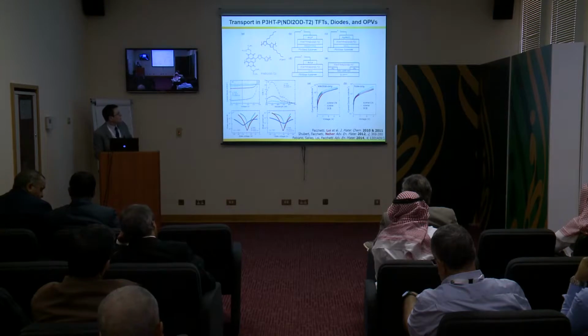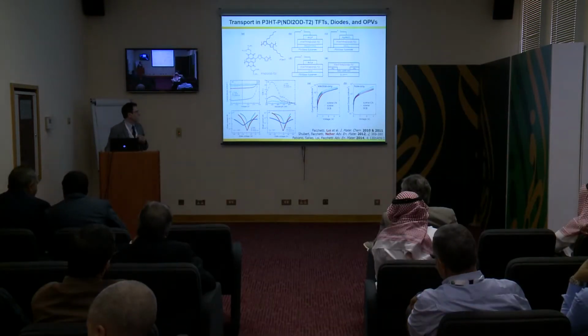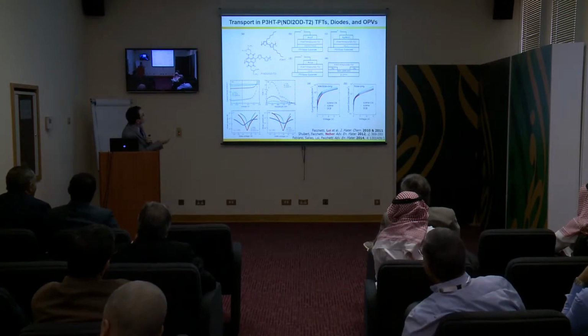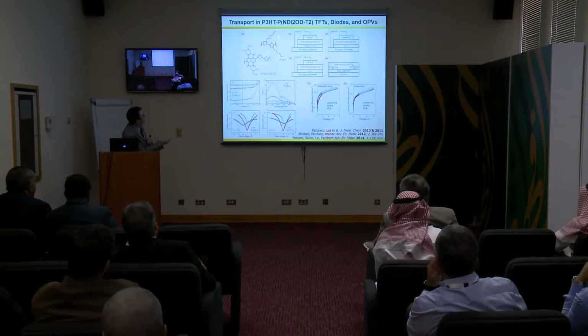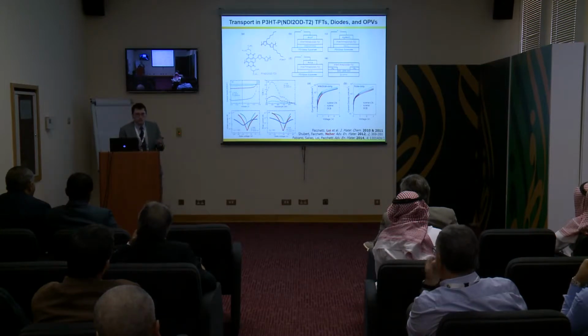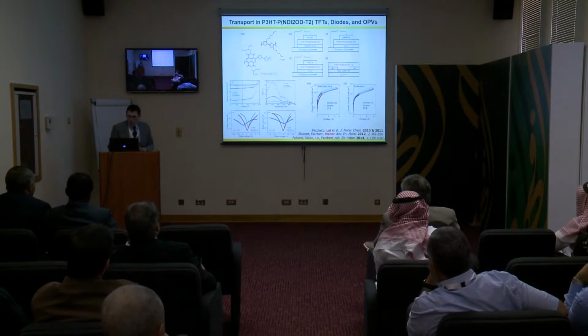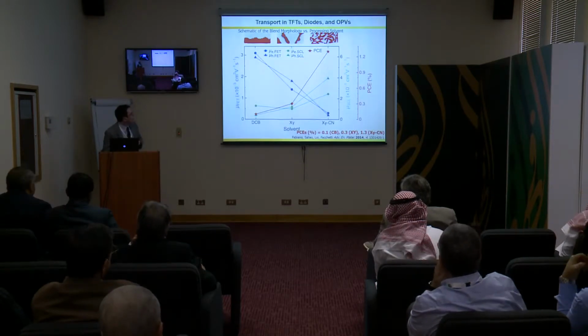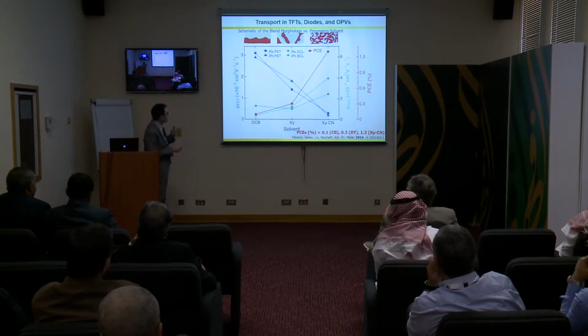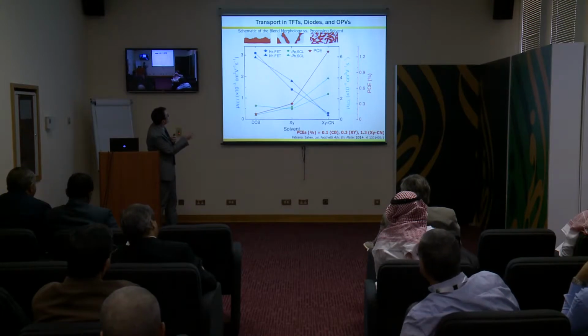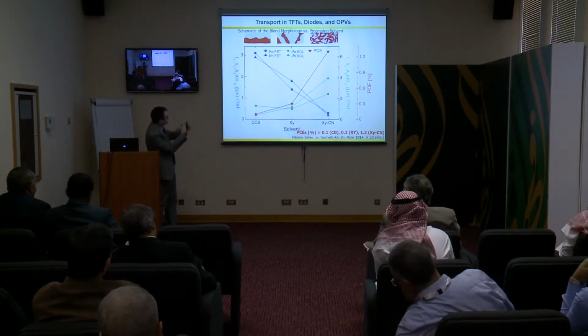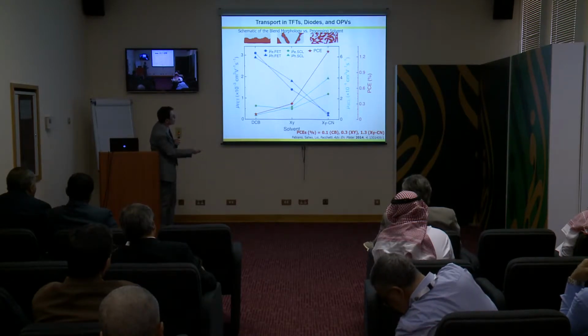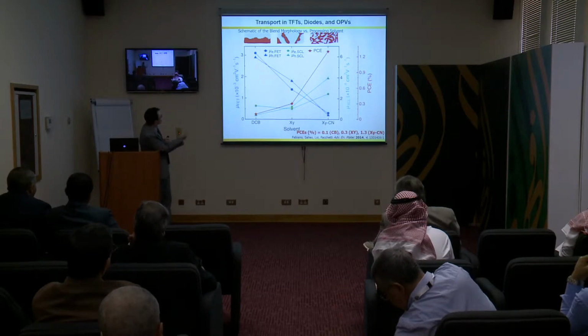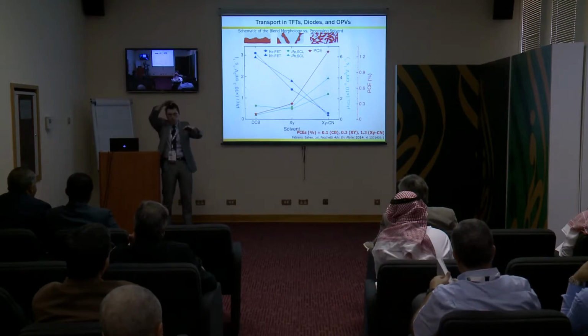We actually started this project way back in 2008, 2009. At that time, we used as a combination of donor and acceptor one of the best donors at the time, P3HT, and one of the best acceptors at the time, this naphthalene diimide type of polymer. We put it together, and the initial efficiencies were on the order of 10 to the minus 3, so quite low. We started to understand better how to process this cell, and this is sort of the best we could come up with. Here is the schematic of the blends of this polymer as a function of the type of solvent you are using to process them. If you use a solvent such as dichlorobenzene, you have a complete stratification. The N-type polymer goes on top of the blend.